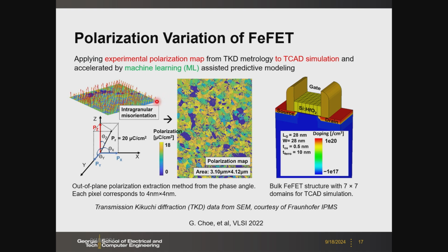Then the polarization value might be different from different locations of the thin film. So here we got the data from the Fraunhofer, and then did this TKD, transmission Kikuchi diffraction imaging, on the as-deposited thin film. And then this is the polarization map measured across the area, let's say 3 by 4 micrometer square. So if you build your transistor at different locations, they may suffer from this polarization variation, right?